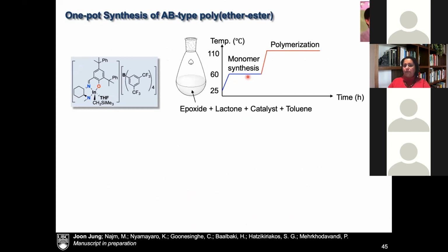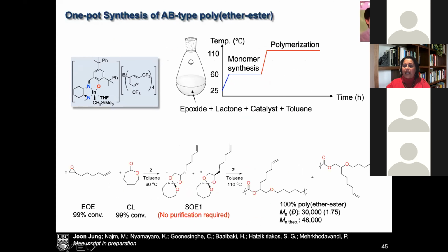So at 60 degrees, we're making the monomer. We know that the system goes to 100% conversion. After it's all converted, we can then jack up the temperature to 110 and then look at the polymerization reaction. And that's what he did. He was able to get really high molecular weight polymer under these conditions without having to purify that intermediate monomer, which is really effectively forming an alternating block copolymer of these epoxide and caprolactone under these reaction conditions.